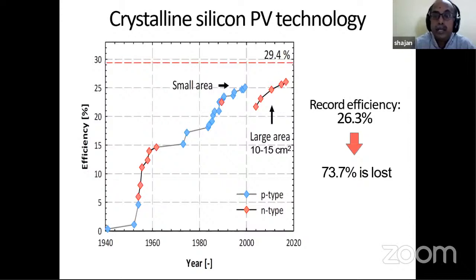And what we are getting now, we have recorded up to 26.3%. We have come up to this level, 26.3%, as being already available. And of course, we are losing 73.7% in the form of recombination and other effects that we will be discussing later. So we are nearing the maximum. Now the available efficiency in silicon solar cells is around 27%, which is very close to this 29.4%. And that is the reason why we are going for other materials, to see whether we can improve the efficiency beyond this 29.4%. That is one reason.